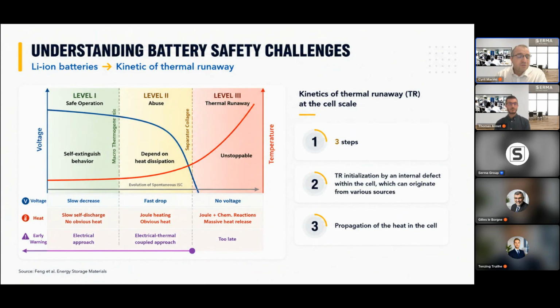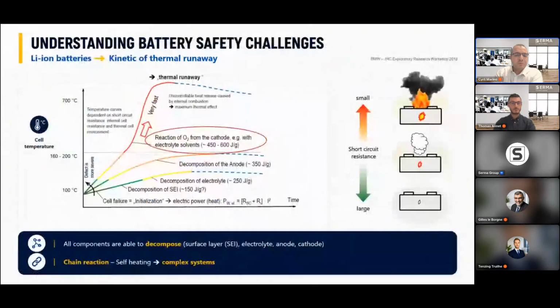But at some point you reach a limit, this red part here, and this limit means that you cannot go back. Even if you put a lot of cold in it, the thermal runaway will happen, whatever cold you put inside. This is very important to understand, because you will see in the next slide that there is a propagation of the heat in the cell. And this propagation exists because you create some heat, and you will see that in the next slide.